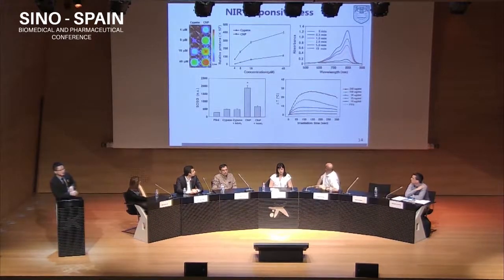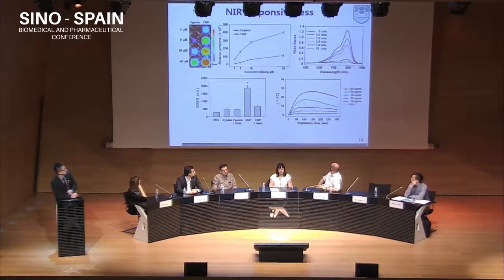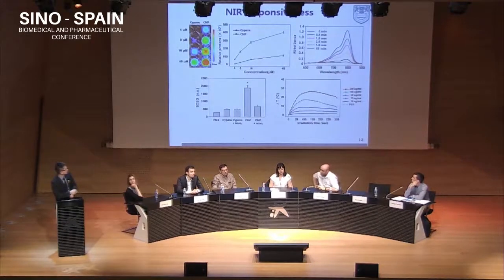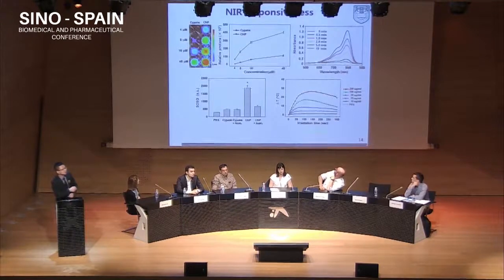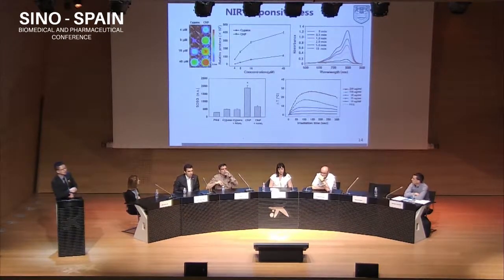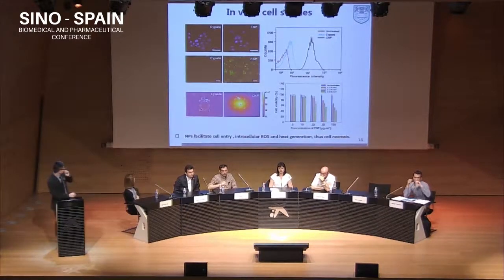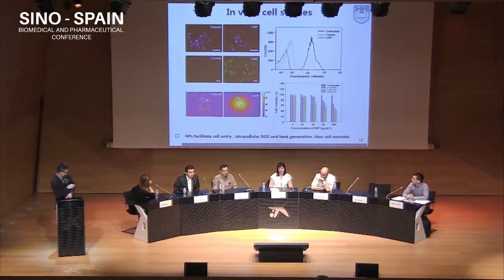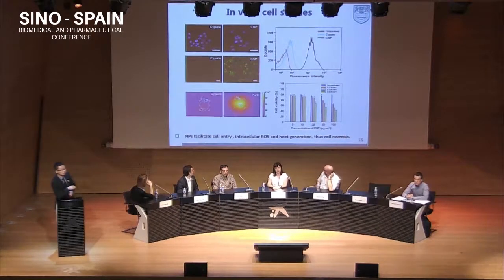And moreover, because ICG itself is photodegradable, this nanoparticle is also rapidly decomposed by light. During this process, ROS and heat can be generated. In cell studies, we found our fluorescent nanoparticle can be rapidly taken up by tumor cells, much higher than free dyes. And also there are intracellular ROS and heat generated in the tumor cells, leading to a strong tumor cell killing effect even under very low light intensity.